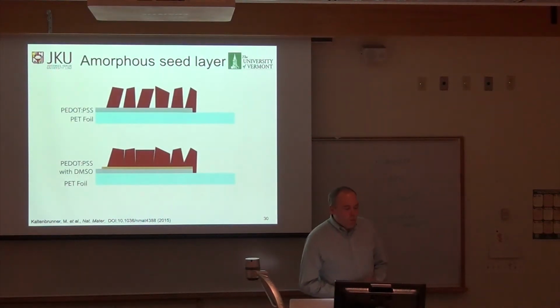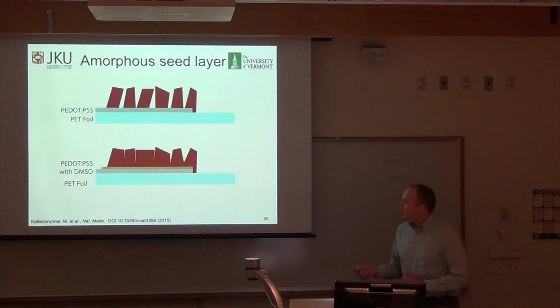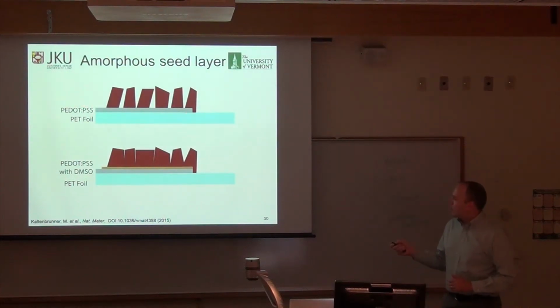So what we came up with was, when we put this PEDOT down on the plastic foil, if we just spin the perovskite on, you get these crystals that grow with massive holes in between, very regular massive holes. The devices won't work at all.